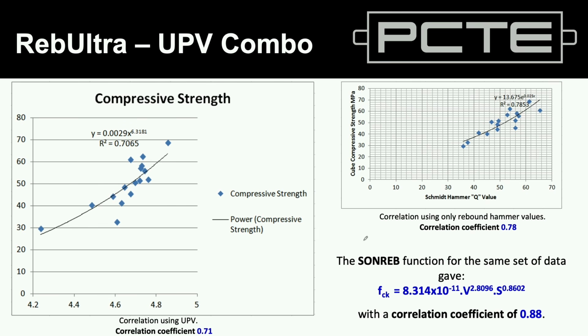It's also possible to go even more tight on your Schmidt hammer testing by combining techniques. So the particular example I've got here is combining ultrasonic pulse velocity testing. We'll talk about that a bit under ultrasonics, but combining a relationship based upon the speed of sound transmission in concrete with rebound factor from Schmidt hammer to broken cylinder samples. And what they've given as the example here is that they've achieved a correlation coefficient of 0.88 for the combined, whereas the Schmidt hammer would have been 0.78 and the UPV would have been 0.71 previously as a correlation quality. So the combination of the two gives a better overall behavior.